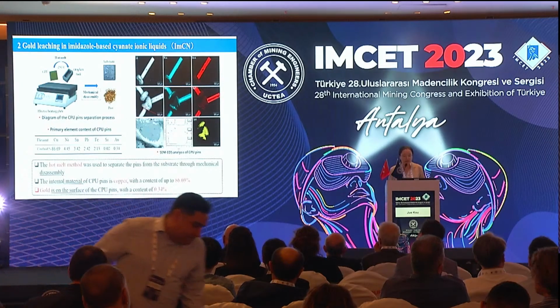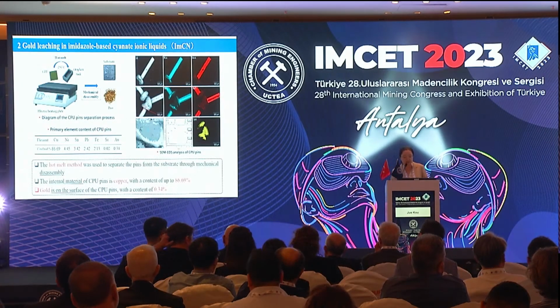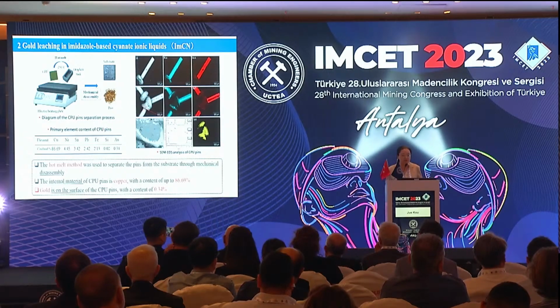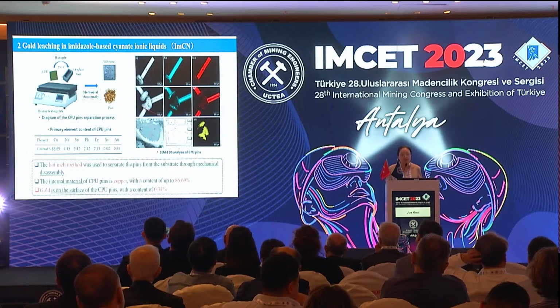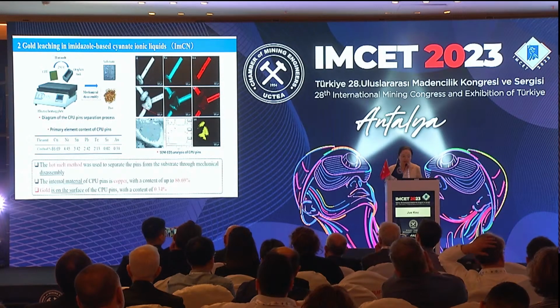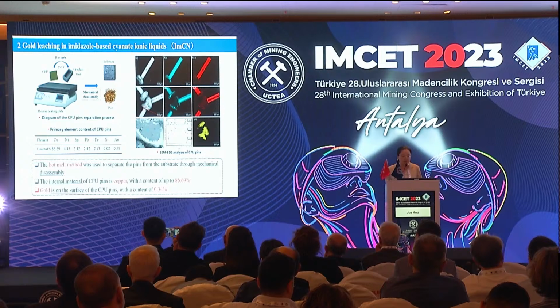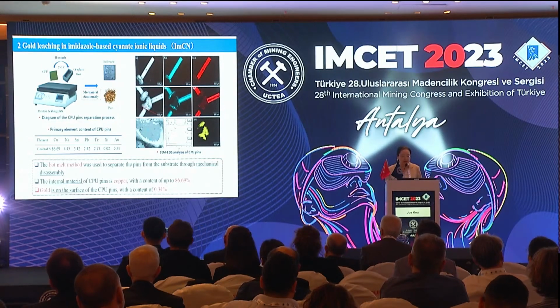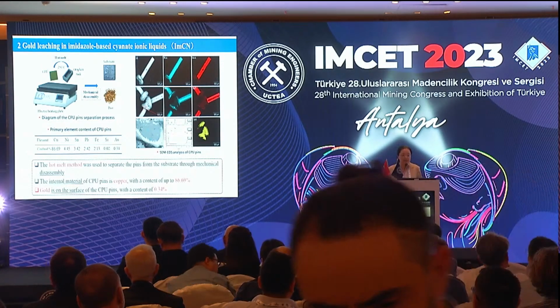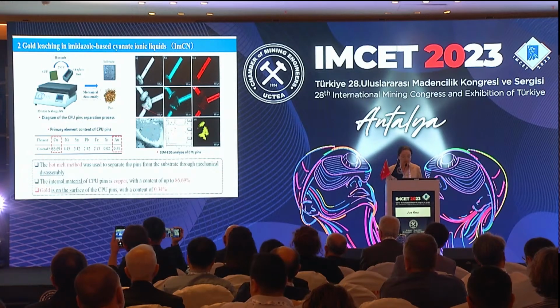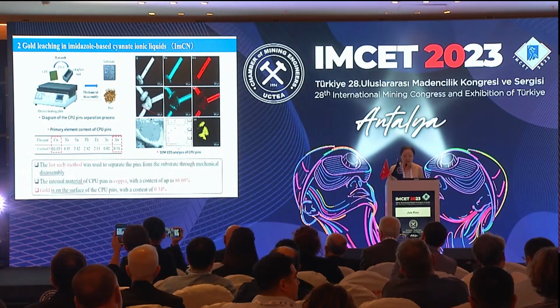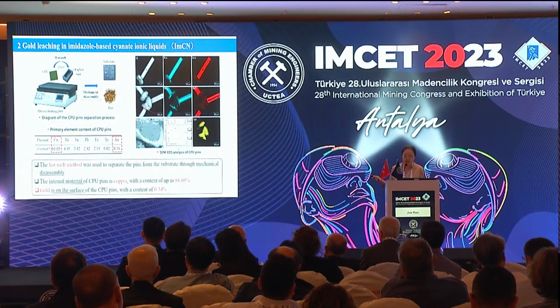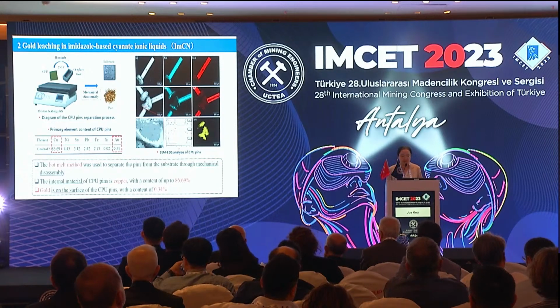And these are the leaching materials we've used in this experiment. We have different types of CPU pins, and we gathered them together and melted them at 250 degrees Celsius to separate the metal from the plastic base. And we have this metal product, which contains about 86% of copper, 4% of nickel, with some lead and iron, and 0.34% of gold. And these are some SEM and EDS analyses of the CPU pins.